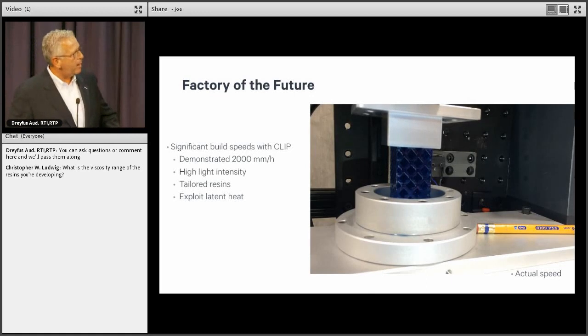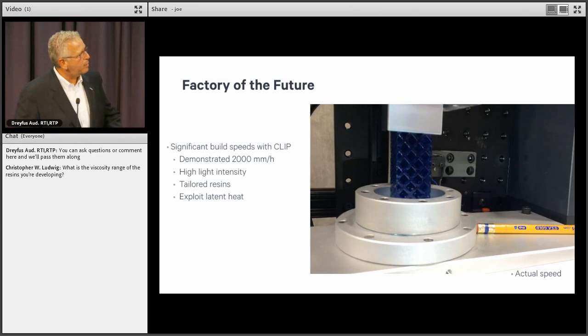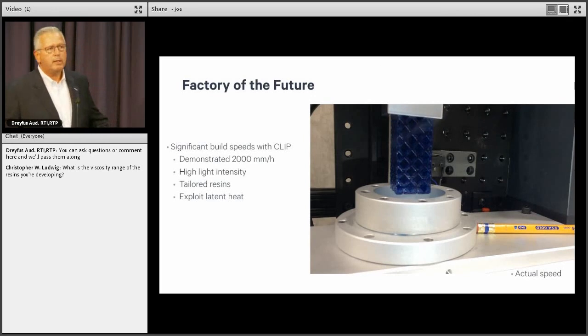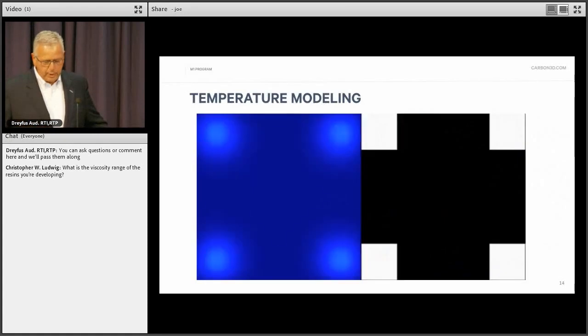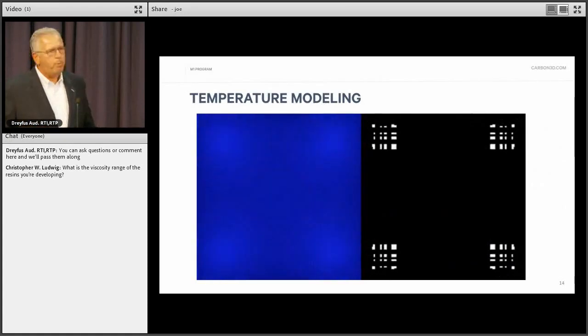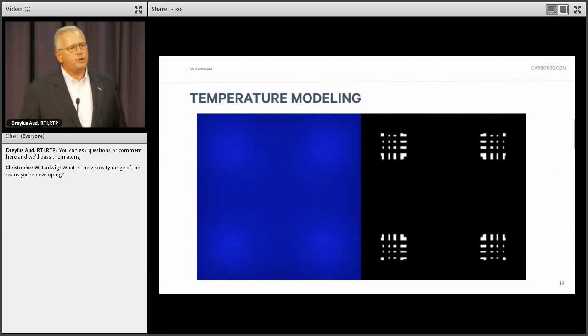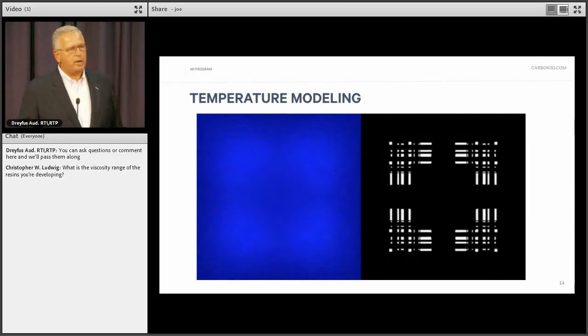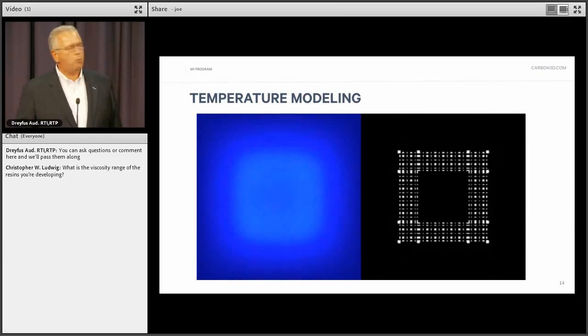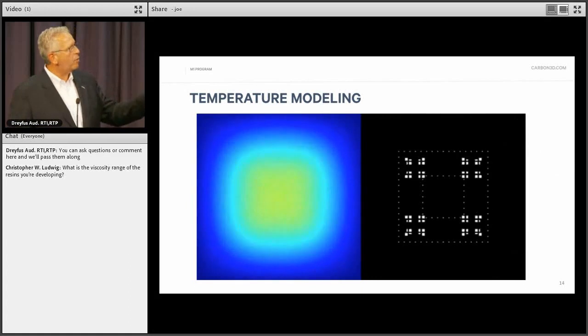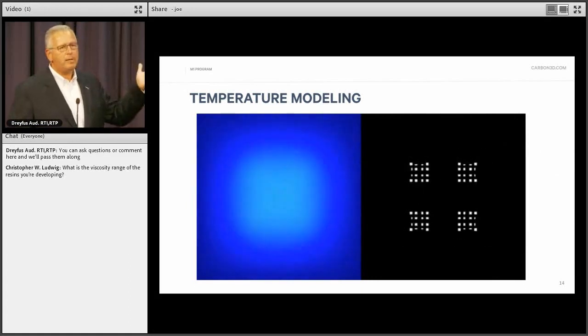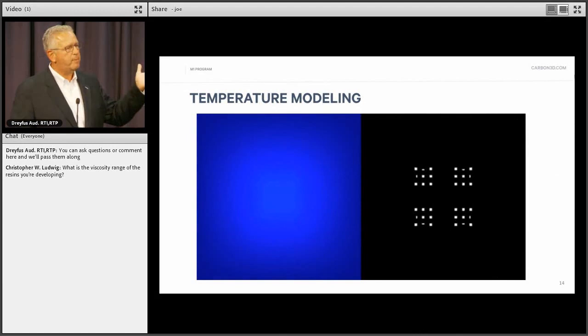And so just to reaffirm some things, this is one of our prototyping printers operating in real time. It's a little hard to see here, but if you look carefully a little bit to the right, you'll see vapor coming off the part. This is smoking hot, right? Free radical polymerizations are exothermic. Think about a situation where you're building a part and it's exotherming as you build it, so the temperature is changing depending on the cross section and the dwell time. This is an Eiffel Tower going through, and you see what's happening in the temperature as a function of time.